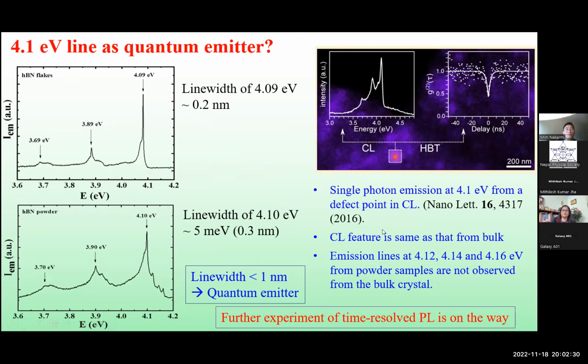So what we observe from the boron nitride is a line emission around 4.1 eV. Most people like to say it's 4.1 eV, but the precise number is 4.09. And if you look at the line width, meaning the full width at half maximum, it is very, very small: 0.2 nanometer for the bulk and 0.3 nanometer for the powder. These kinds of emissions we see from an atomic spectrum. So that's why we are calling it atomic-like emission.